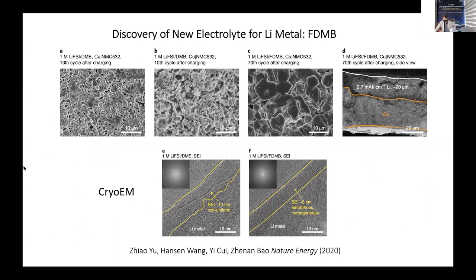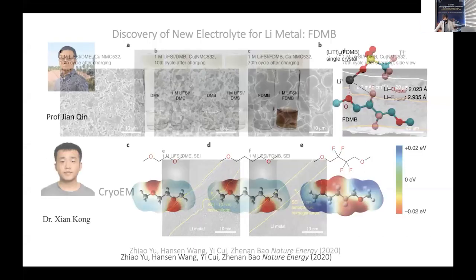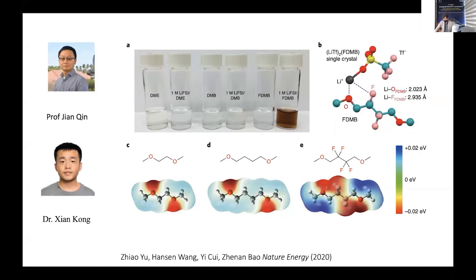There's also another reason why this new electrolyte is so good. Through simulation, in collaboration with Prof Jian Qin in chemical engineering right here at Stanford and his postdoc, we found that the oxygen and fluorine in this FDMB molecule can coordinate with lithium. If you look at figure A right here, the brown color electrolyte is the FDMB one. Usually a lithium electrolyte shouldn't have color, but because of this ring pattern of coordination, it generates a very different effect. We also found that this coordination has a lot of anion coordination in the solvation shell as well. So once it decomposes to build the SEI, it has an anion-rich SEI that's more stable for lithium metal deposition. So more to come in explaining why this electrolyte is good. We will have another new publication hopefully coming out soon to explain this in detail.